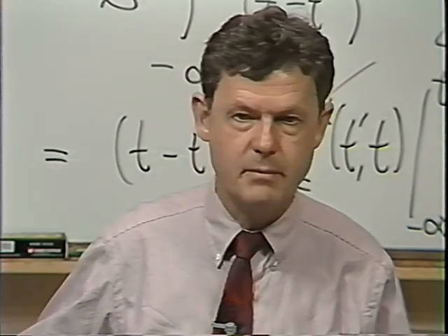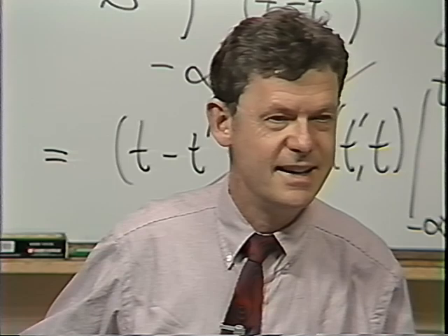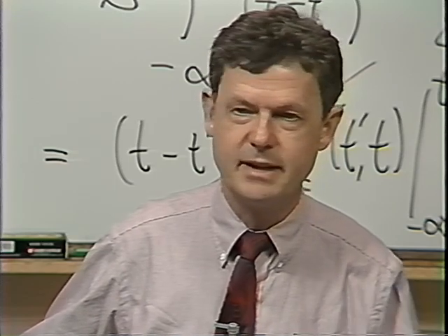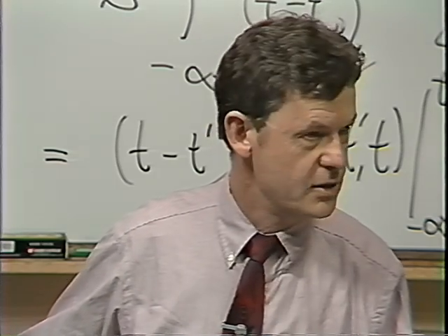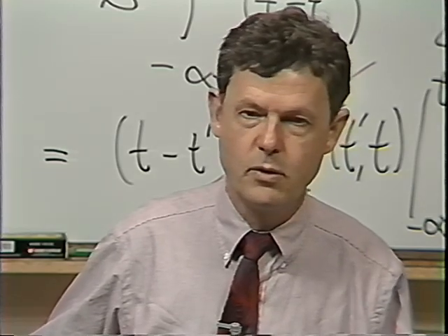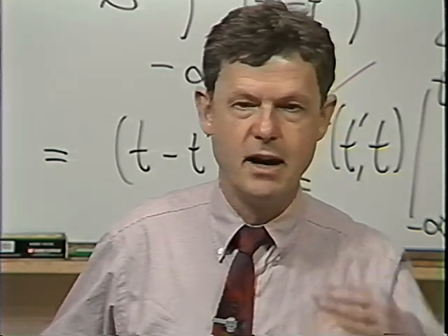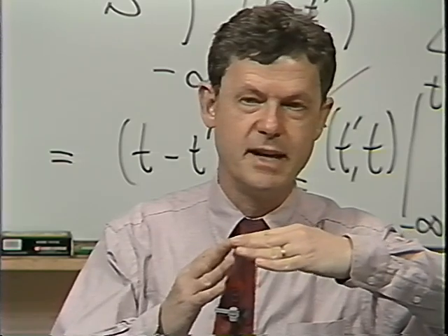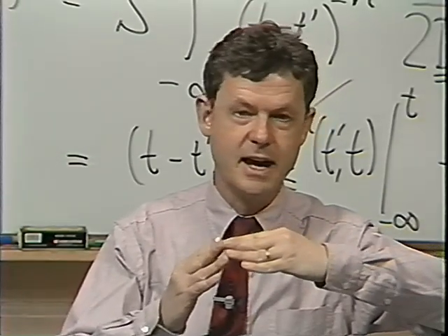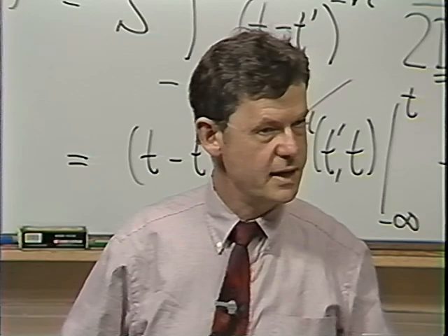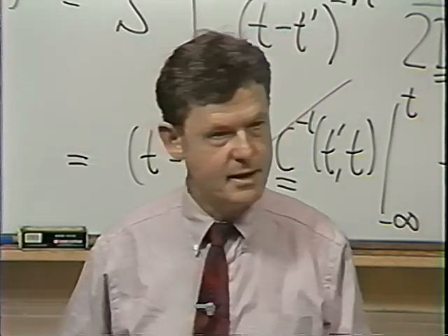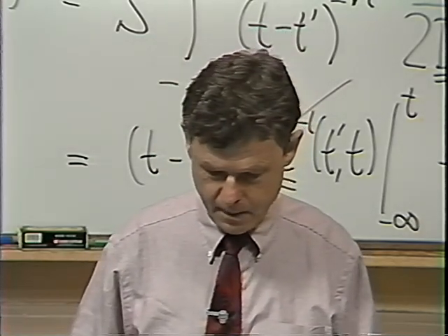We should do the same thing for the material in the gel, beyond the gel point, and again we would get the same exponent. So this definition which I used before, this 1 over omega of the break point as a characteristic time, is really giving us the same result as the analytical picture which we have here.